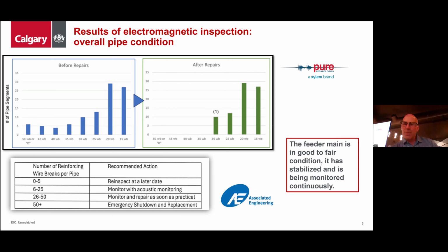But we did identify, through the use of the pipe robot and the pipe diver, a total of 239 locations of the 16-foot deteriorated pipe. As I said, the pipe is significantly deteriorated in spots, in addition to the pipe that had ruptured. But let's put this in context. Of the 239 sections of 16-foot pipe, there are over 2,000 pipe segments in this particular feeder main. So roughly speaking, quick math, about 10% of the pipe we are finding with some form of structural deterioration. So the majority of the pipe is still in good condition.